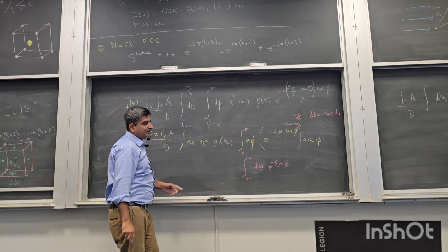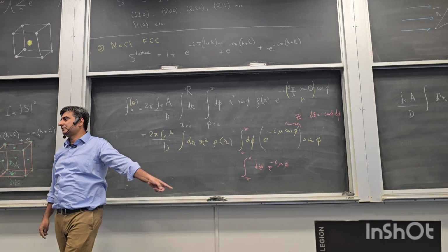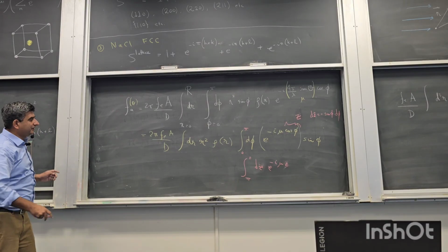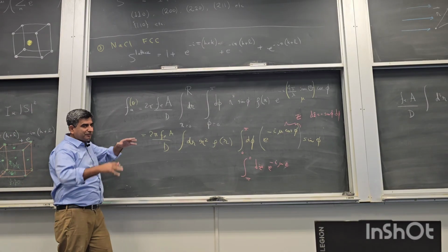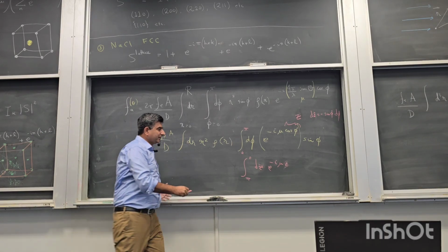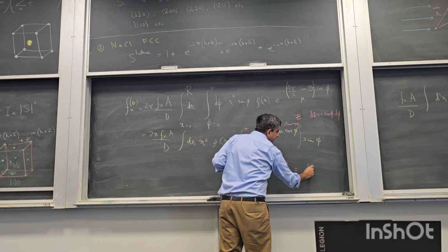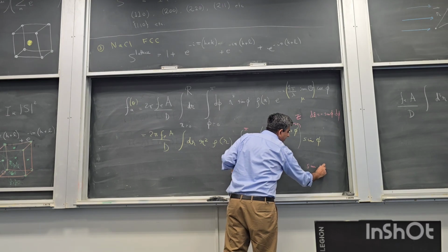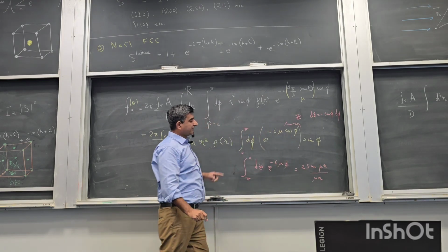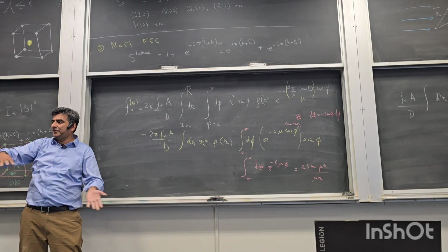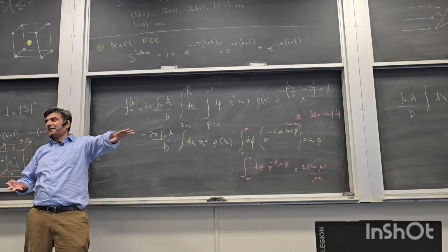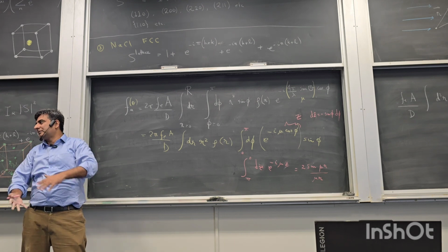Okay, this will be a sinc function. The integral of this will be a sinc function. If I plot this, the integral is sine mu r over mu r. It's going to go down with mu, where mu is the angle. So for large thetas, this factor goes down.